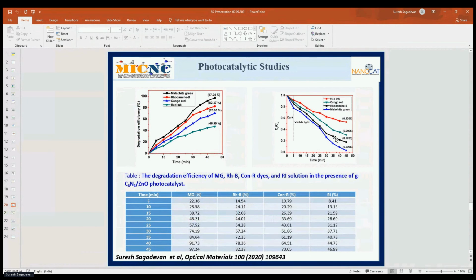The next is the Ct/C0 versus time graph. You can see that graph. The figure shows that Ct/C0 is strongly affected by the irradiation time. The changes in the concentration of the 4 dyes along with time were recorded, and you can see that it can be observed from the figure. The photodegradation of all the tested dyes and solutions is extremely slow in the dark. You can see that red ink shows 0.53, Congo red 0.29, rhodamine B 0.1763, and malachite green 0.0276. So this is the visible light elimination for this composite.